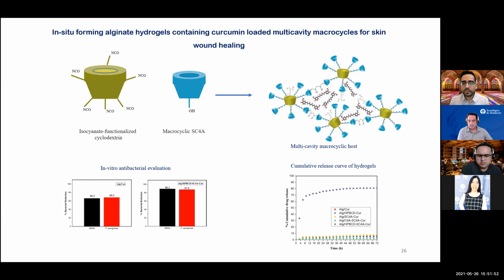Thank you, Said. Said, have you read something about the roughness of this hydrogel material? No, we didn't do any experiments regarding the roughness, because most of the tests are regarding the antibacterial activities and the cell viabilities, and for the dosage system that contains some nanoparticles, we only did some XRD and FTIR for analyzing the systems. However, if we want, we can use different techniques. For example, we can use AFM, atomic force microscopy, to study the roughness of the surface. If we want only the morphology, we can use scanning electron microscopy, but I think if we use the AFM, we have a better result regarding the roughness of the surface.